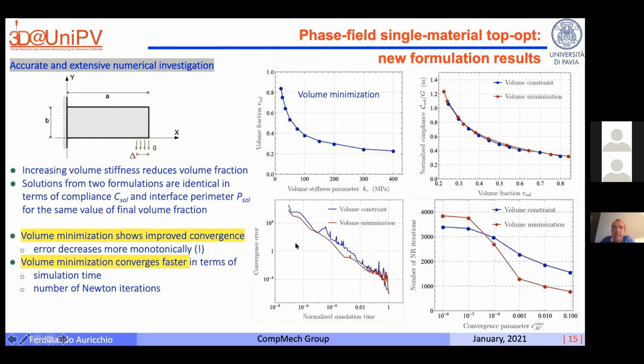But the very nice thing is down here, where we plot convergence versus the simulation time. And the red curve is much more uniform than the blue curve. The blue curve is the volume constraint approach, the classical approach, while the red curve is our approach. So this new formulation seems to behave much better from a numerical point of view. And you can see the results also here, where we have the number of iterations, and with the red approach, the volume minimization, we easily get fewer Newton iterations to obtain our solution.